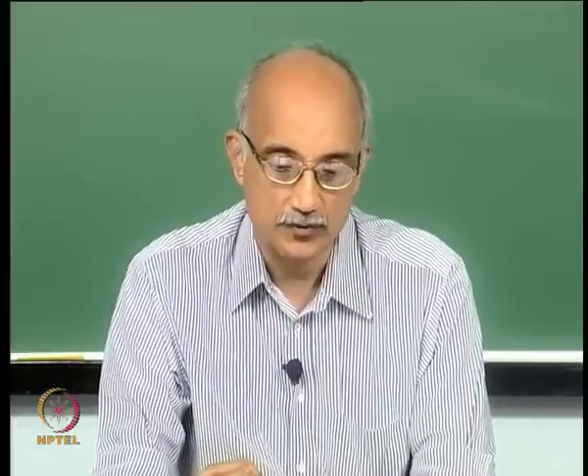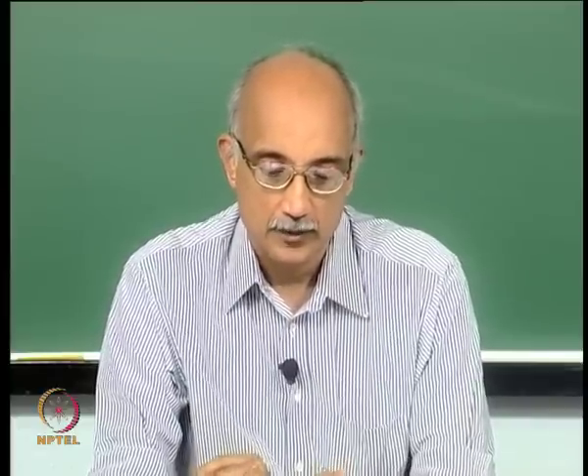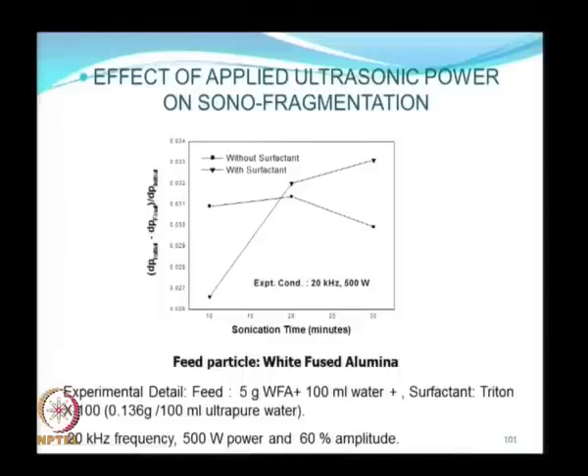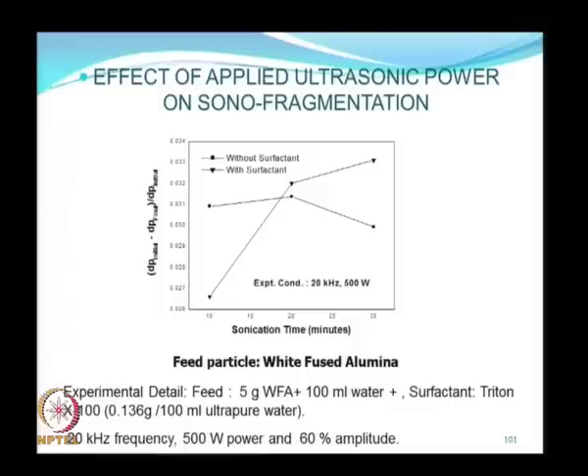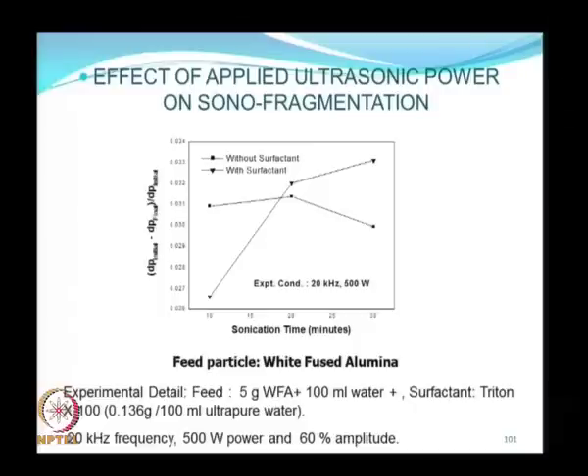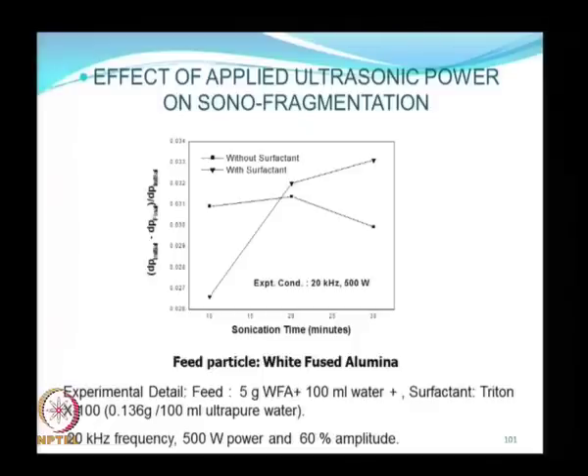If you compare the graph with surfactant and the one without, without the surfactant, the fragmentation rate is eventually equal to or exceeded by the rate of agglomeration. So, even though you may be fragmenting the particles by ultrasound, they will reattach or re-agglomerate, and therefore there is no sustained particle reduction beyond a certain time. However, with the use of surfactant, as you increase the amount of sonication time, the size reduction keeps increasing, although the rate of size reduction does tend to reach a saturation point.